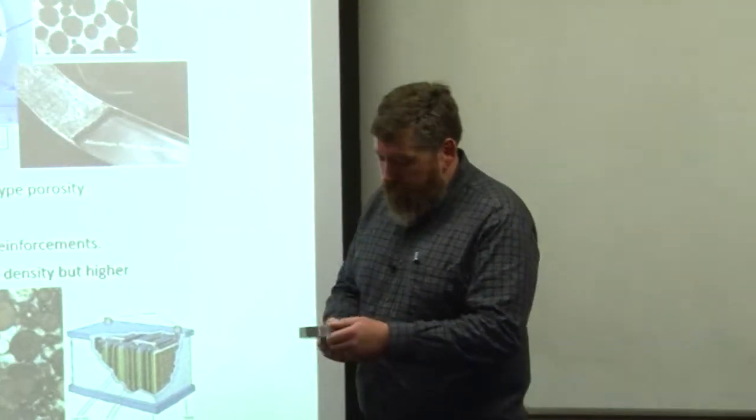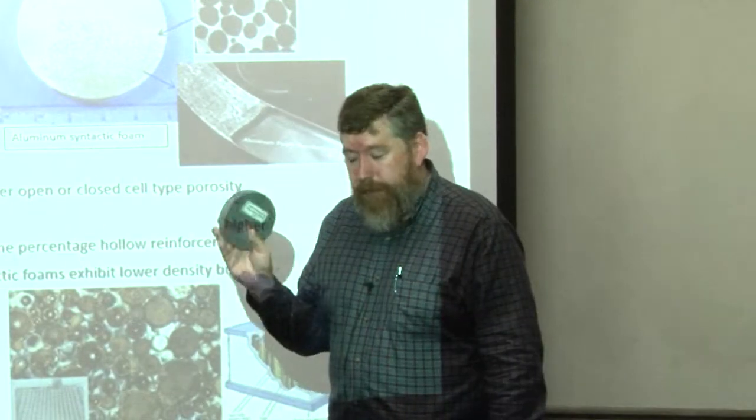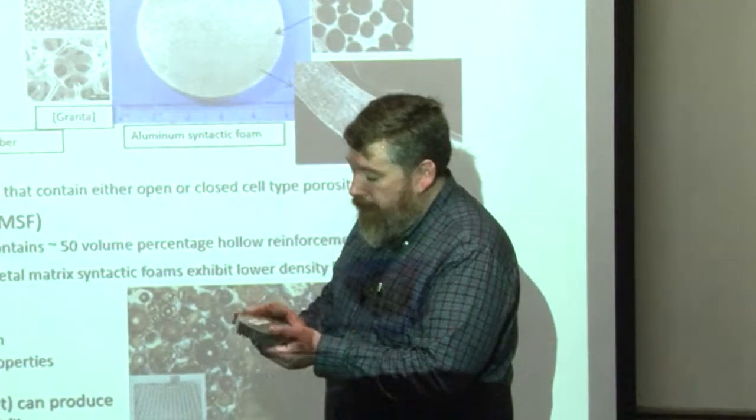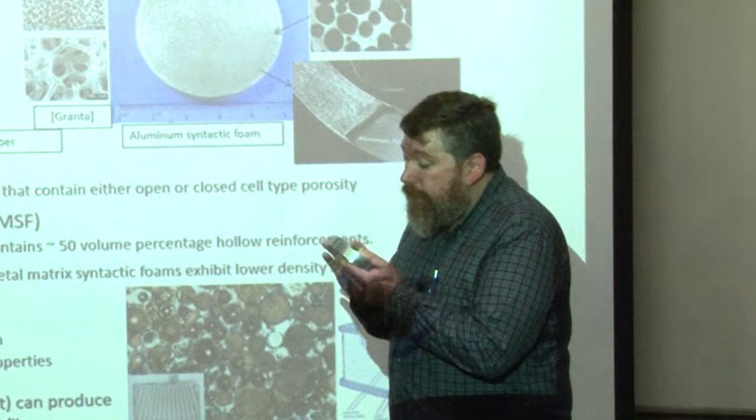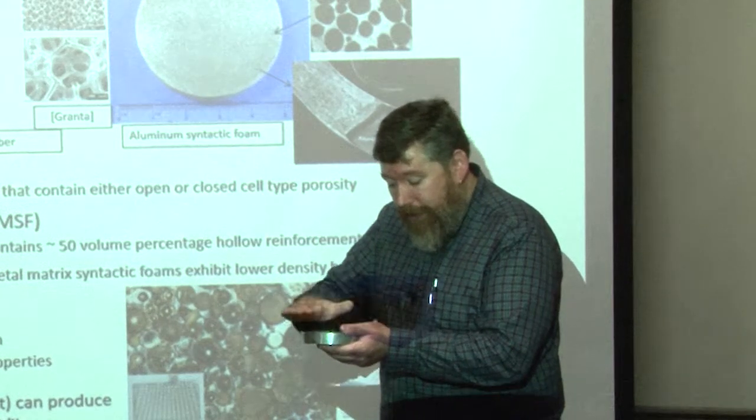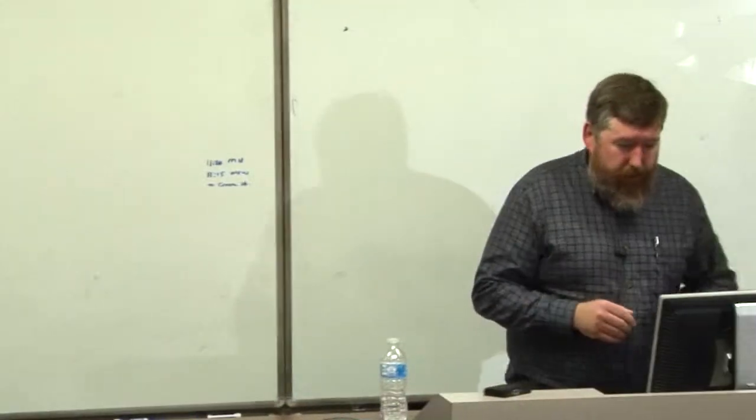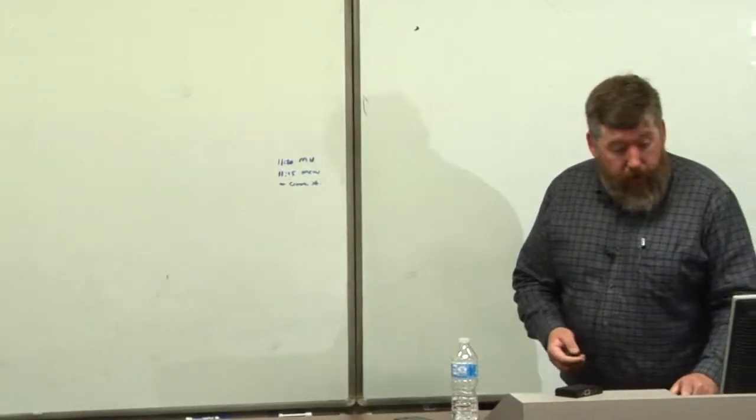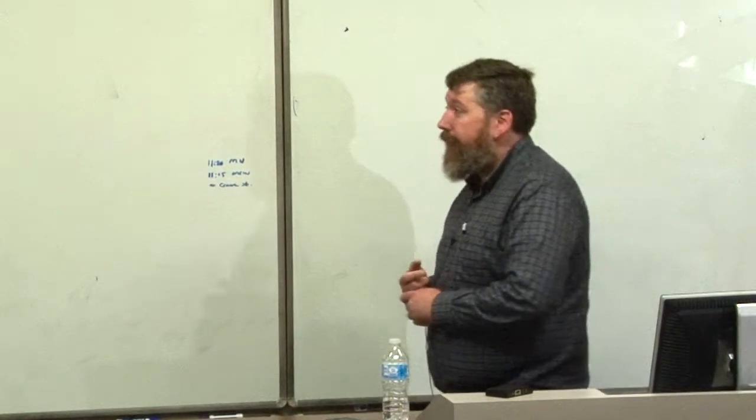The syntactic foams are a type of composite foam so instead of having just pores we have hollow particles creating the porosity. This is aluminum, this is A206 which is an aluminum copper alloy, high strength alloy. This has aluminum oxide hollow spheres in it and if you look very closely at this when I pass this around you can see these little look like little pin holes. Those are the spheres that have been cut in half. So on that surface you're seeing the holes that are inside those spheres. These have all kinds of applications for energy absorption and also reducing the weight.